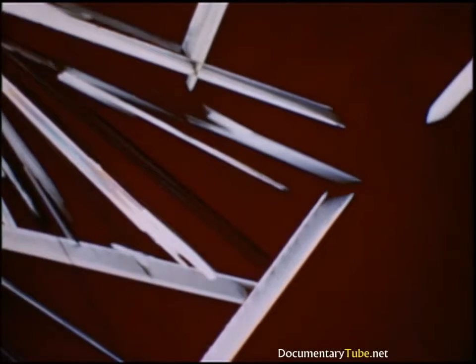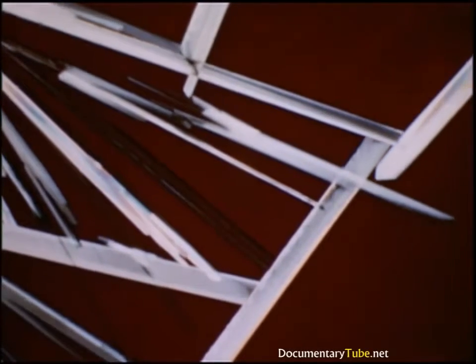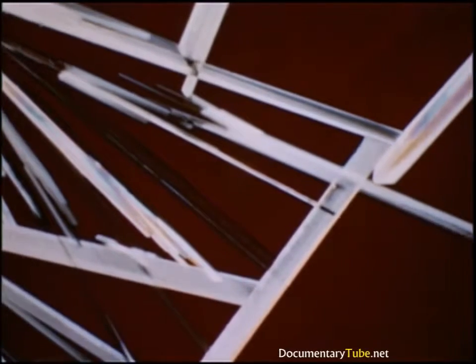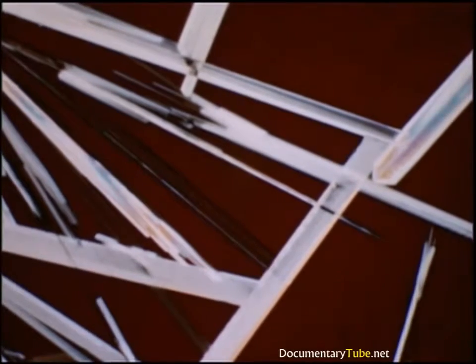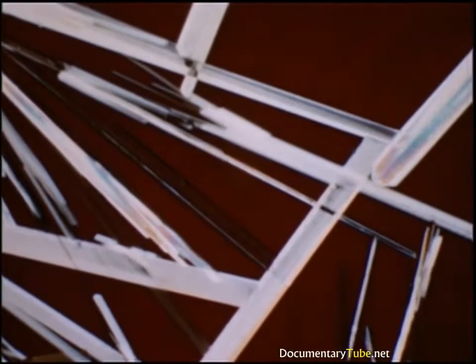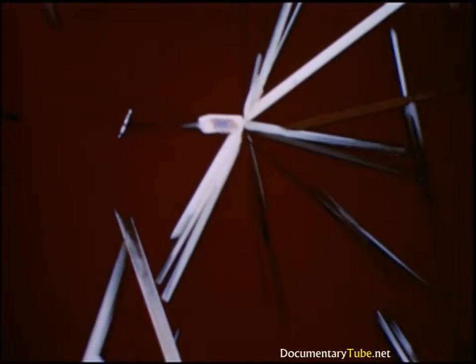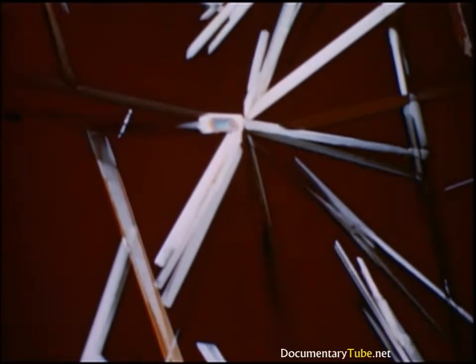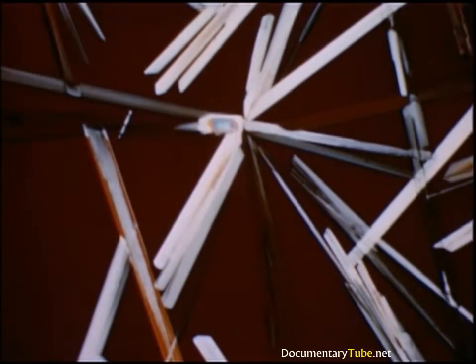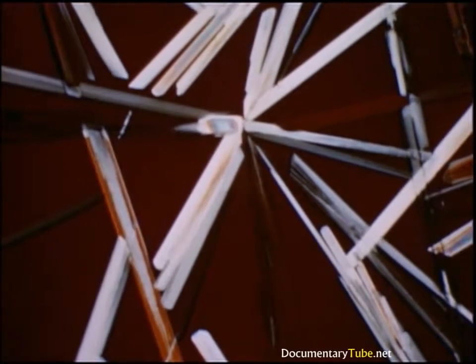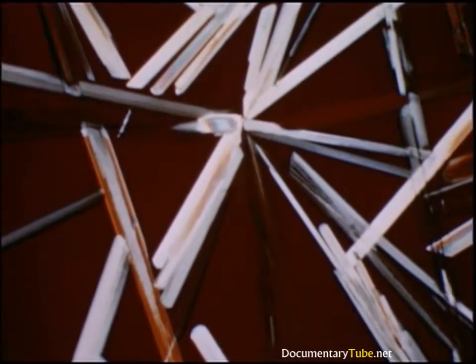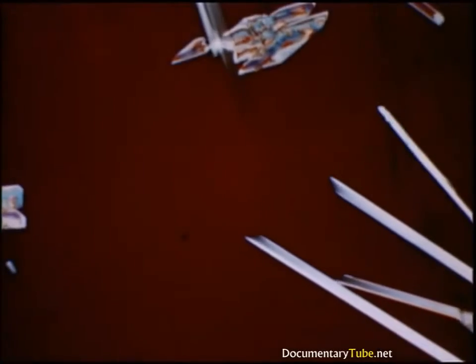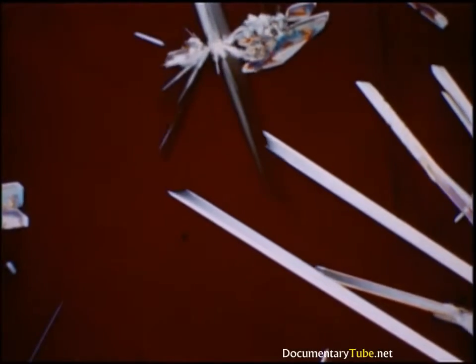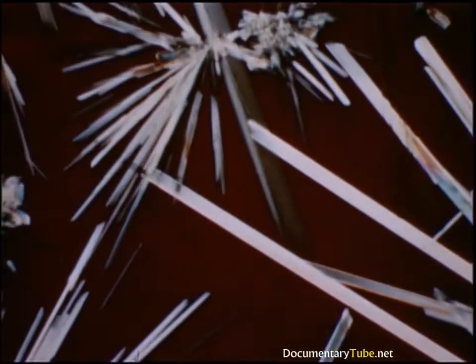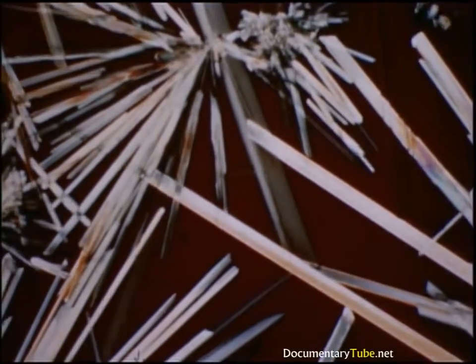Magnesium chloride, magnesium oxide, and water form an interlaced network of crystals, such as you see forming under the microscope, magnified thousands of times. This network embraces all of the ingredients compressed into the brick and gives it tremendous strength, as cement does in the setting of concrete. When the brick is fired, the chemical bond is gradually replaced as the firing heat produces the ceramic bond.